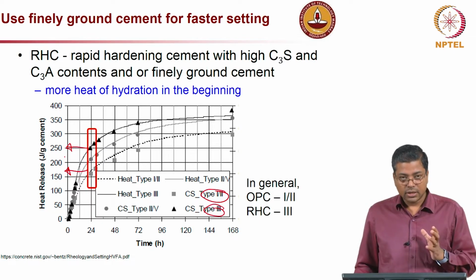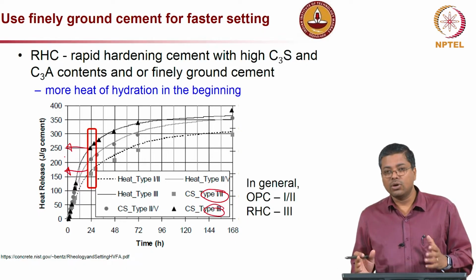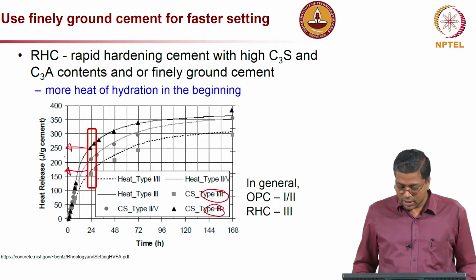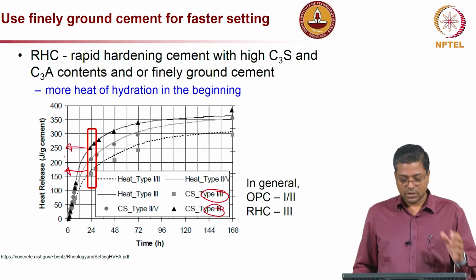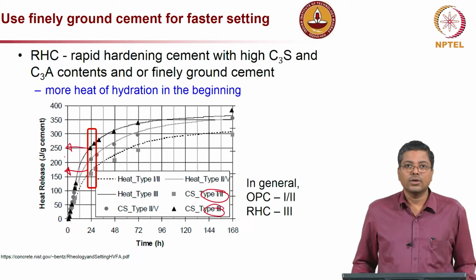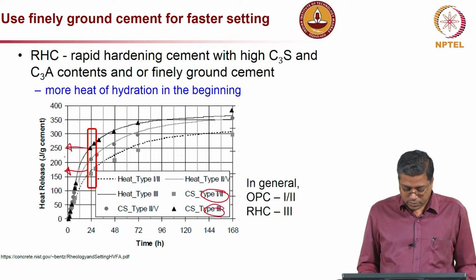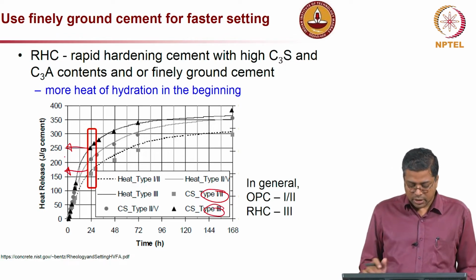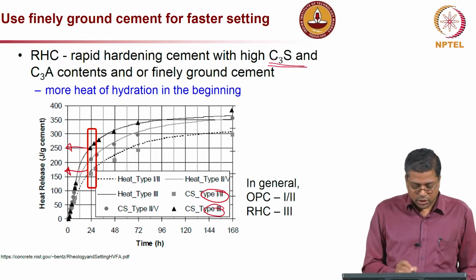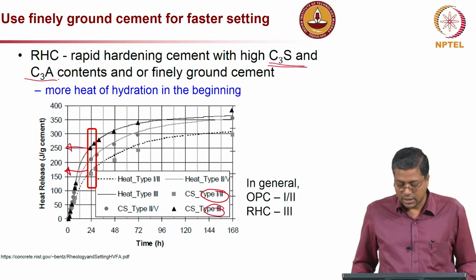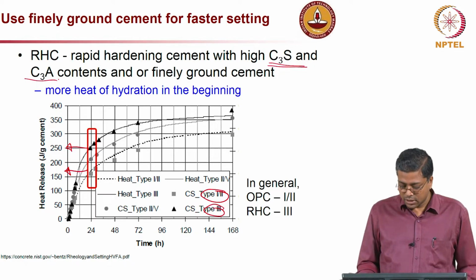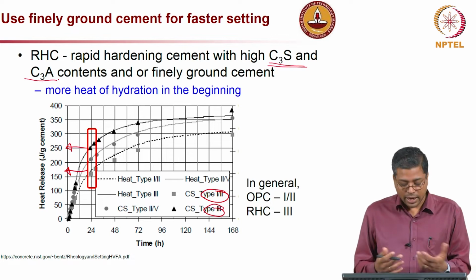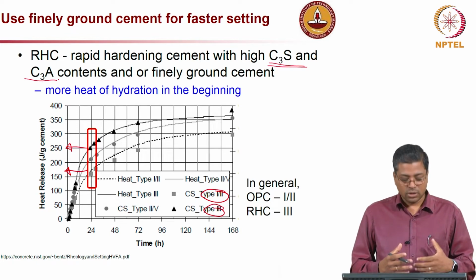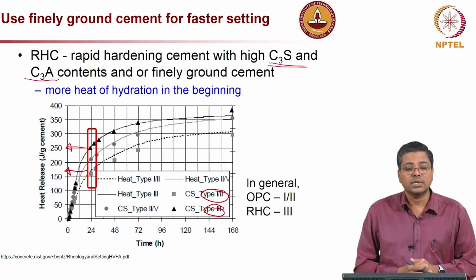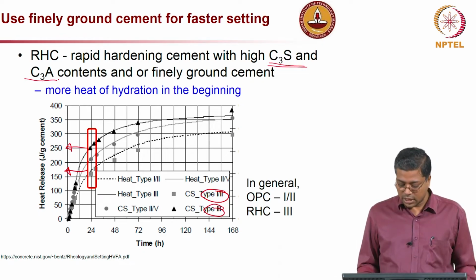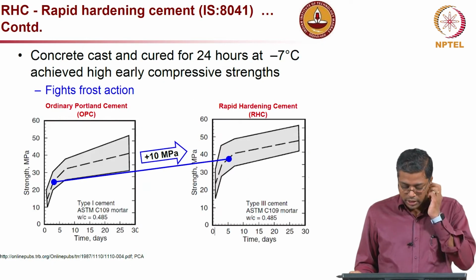So, that heat is very good or necessary for the hydration for the concrete to get cured better or in an accelerated manner. And also we can use high C3A and high C3S cement, which will help in making sure that there are more and more reactions, especially in the early stages of curing or hydration.